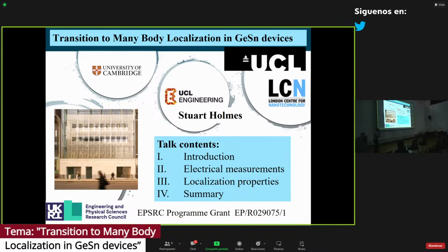Now, I've spent most of my research career in industry, and when you're in industry, you always think, what's the product? Why are we doing this? How much money are we going to make? But it turns out germanium tin is quite useful because germanium, as we know, is a semiconductor, and it's nearly a direct band gap, but it's not. If you strain it or add tin to it, it becomes a direct band gap. So that opens the whole field of optics and photonics to a silicon platform. So it's very attractive to industry.